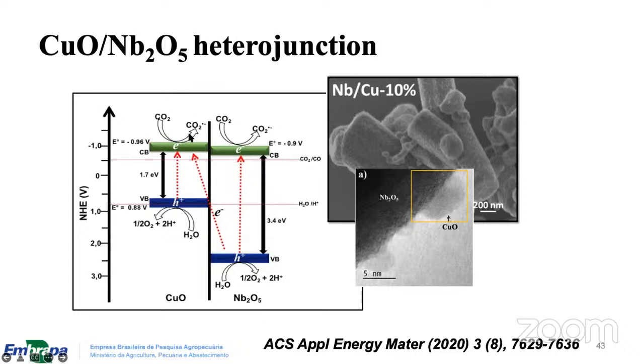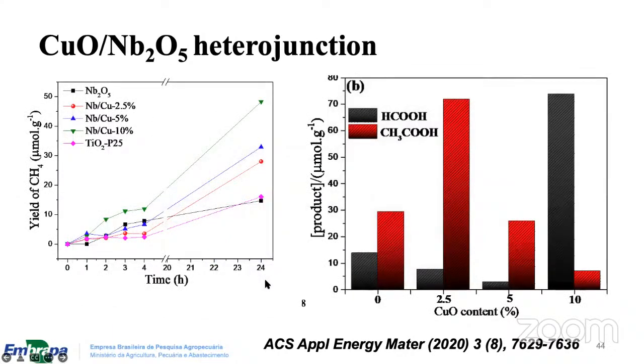The copper oxide is more prone to pump electrons or to concentrate the electrons in the conduction band, whereas the niobium oxide is more likely to have the concentration of the holes here in the niobium oxide that would be responsible for the oxidation reactions. So what we observed is that this system is in fact more stable. It can be used for longer times than the system with only copper oxide.